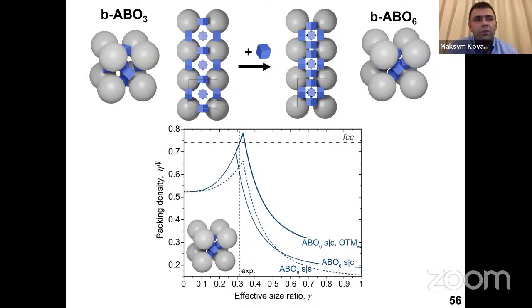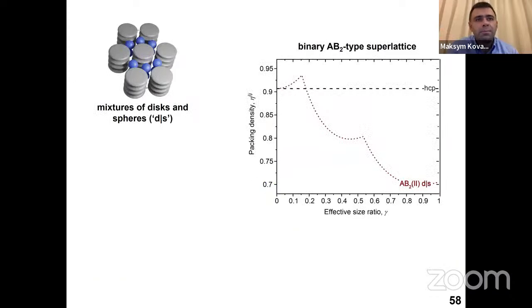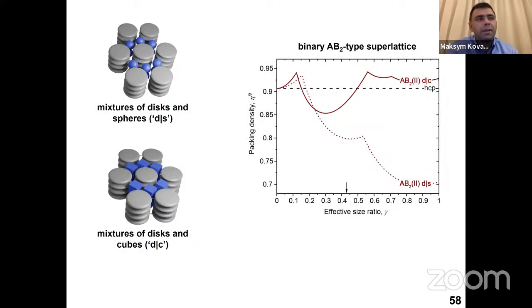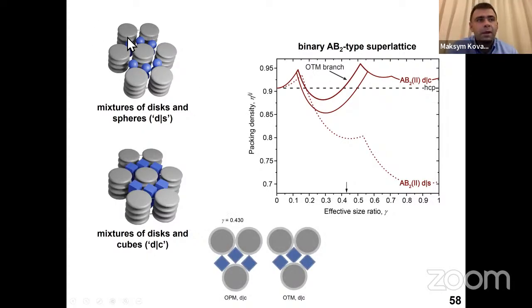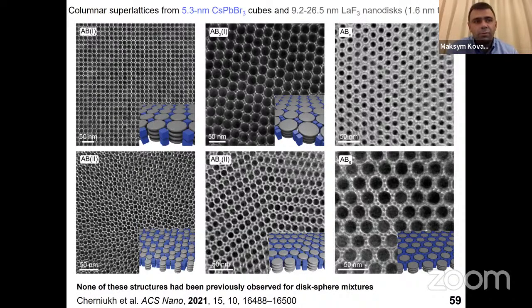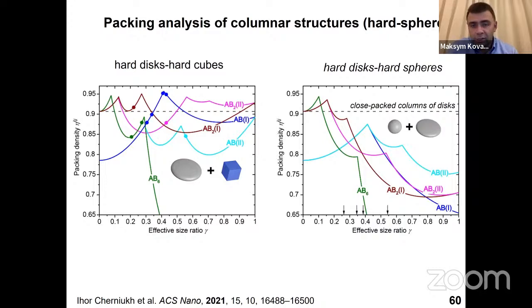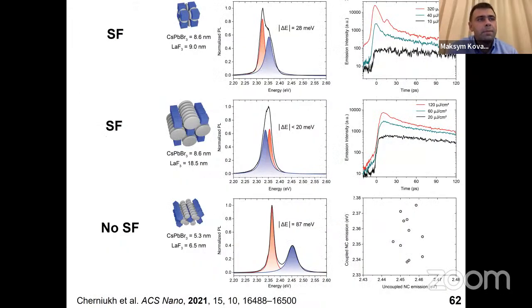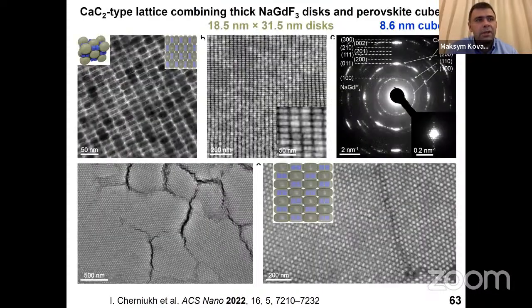And we have discovered a whole bunch of new lattices, which I will skip because of the time matter. But I will just tell you that also when you combine cubes and disks, you again will observe new lattices, which you cannot see when you combine spheres and disks, because these structures have higher packing density. As you can see, for instance, if you compare the space filling curves for this case versus the space filling curve for the sphere disk mixture. And so we have discovered the library of these ones for different sizes of disks and sizes of cubes. And again, there is a structure property correlation